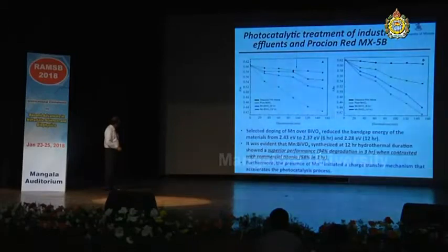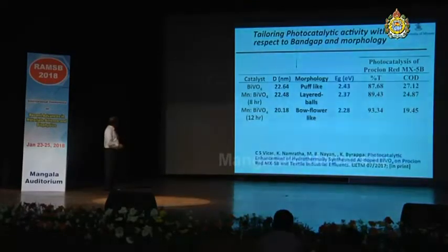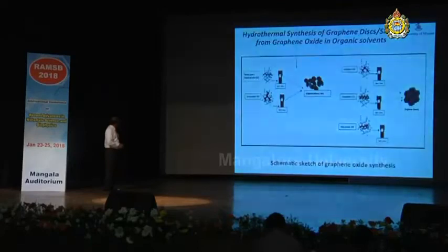They showed a superior performance, like 94% degradation in about 3 hours time when contrasted with commercial titania, which gives about 58% in 3 hours. And this is pure bismuth vanadate and manganese doped, the experimental duration, and the COD, that is the chemical oxygen demand, and the percent transmittance of the dyes or the effluents, and the variation in the morphologies, bowl-like flower, and layered balls and puff-like structures we have obtained.